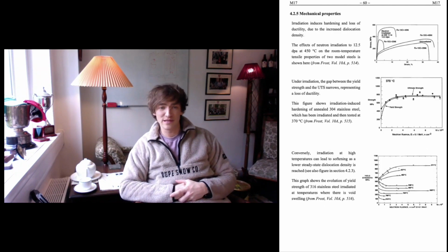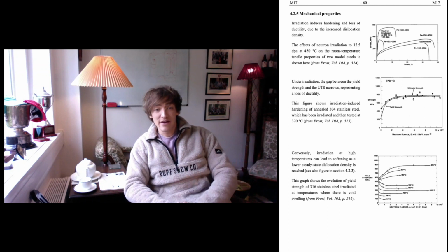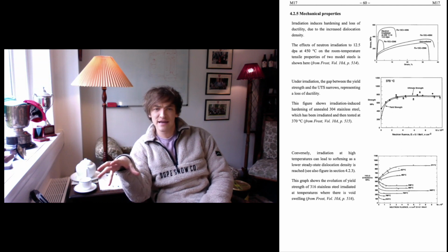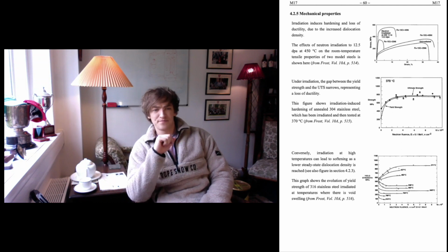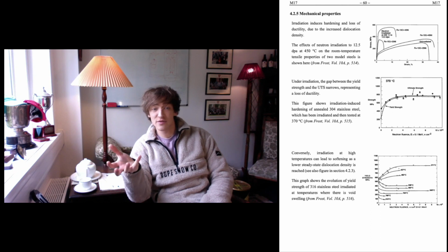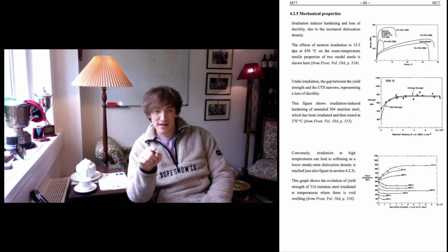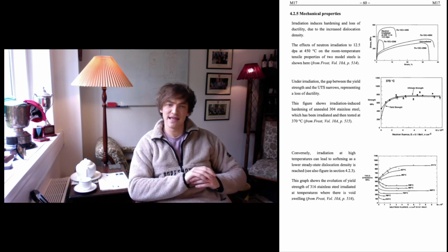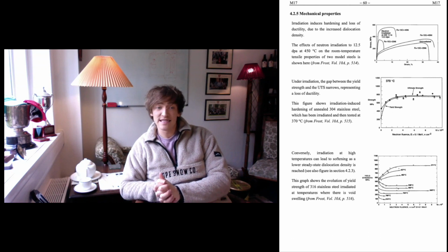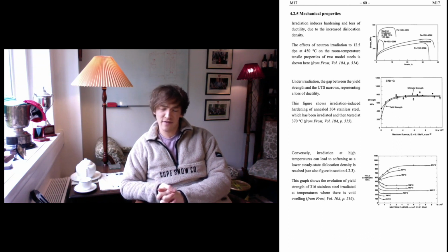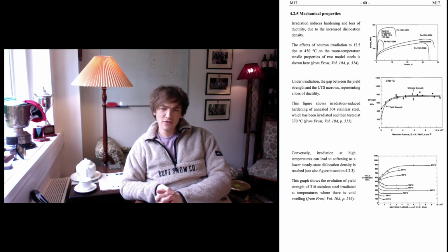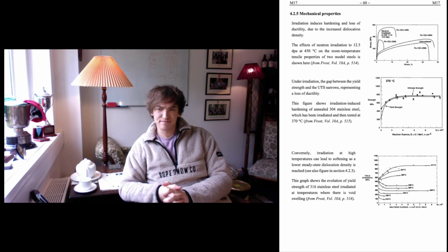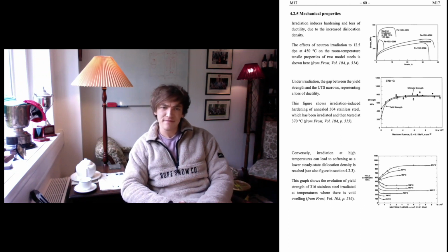What about mechanical properties? Well, again, we get irradiation hardening and a loss in ductility on account of the increase in dislocation density, and that's shown in the top right graph. However, like I've said, the effects are temperature dependent, as shown in the bottom right graph. That shows that at high temperatures, irradiation can lead to softening as the lower steady state dislocation density is reached. So you've got yield strength on the y-axis, neutron fluence on the x. High temperature, you get something very different to low temperature. You get hardening or softening. Okay.